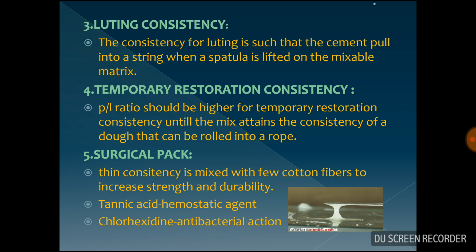Temporary restoration consistency. The mixing is done with a high powder to liquid ratio until the mix attains the consistency of a dough that can be rolled into a rope. Such a proper mix can be condensed well in place. If too little powder is used, then the mix becomes sticky. If too much powder is used, then the mix becomes crumbly.